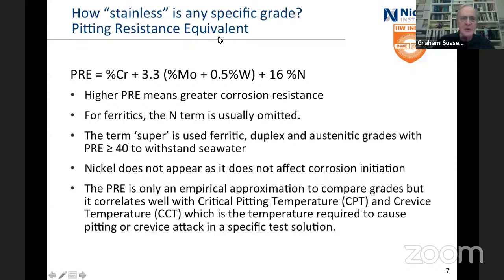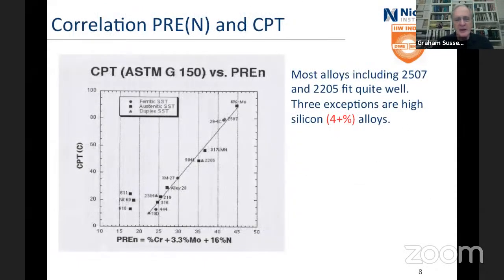This pitting resistance equivalent is an empirical approximation, and it's designed to compare grades, but it correlates really quite well with the thing called the critical pitting temperature and the critical crevice temperature, CPT and CCT, which is the temperature required to cause either pitting attack or crevice attack in a specified test solution. It's not looking at what happens in the real world. It's looking at, here we are in a test solution, what has actually happened. And here is a little example.